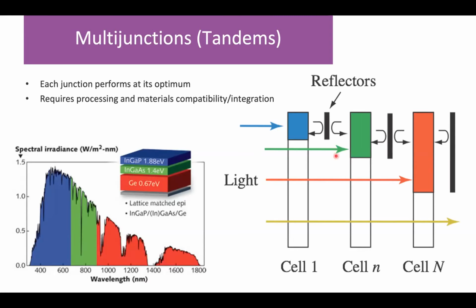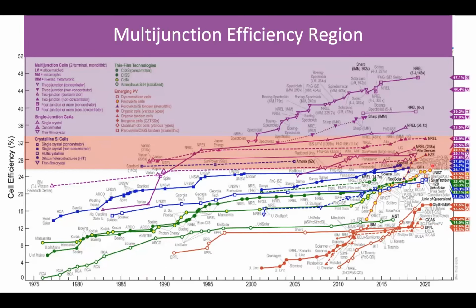But we are looking at all perovskite tandems. And at the moment, actually, I'm going to probably just go to the next one. If you look at what state of the art is, right? I mean, so 25.5 is pretty good tandem, right? Here, the silicon perovskite is a pretty good number. So a tandem's got to be pretty good. But the silicon perovskite tandem is well above this one, right? So we can add really, really good solar cells that have taken all of the learning curve from all the silicon technologies over the years and really kind of pushed it farther.